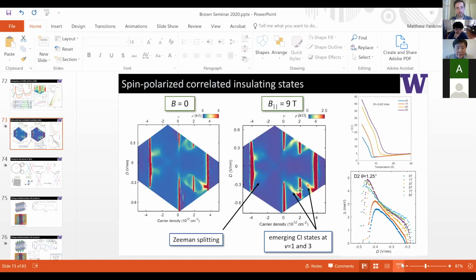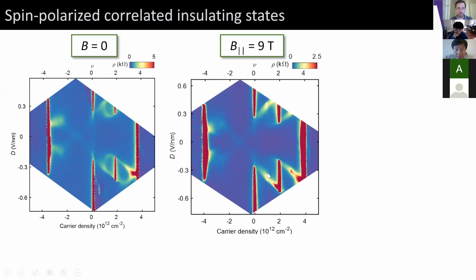Both in plane and out of plane? That's right. There's nothing like a very sharp transition as you would expect for a superconductor, for either in plane or out of plane. When we apply an in-plane field of 9 Tesla, you can see that the resistance within this halo-like region doesn't change substantially from zero field, but you do stabilize these correlated insulating states more strongly.